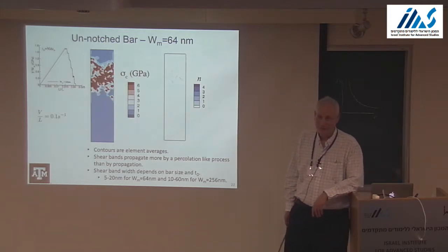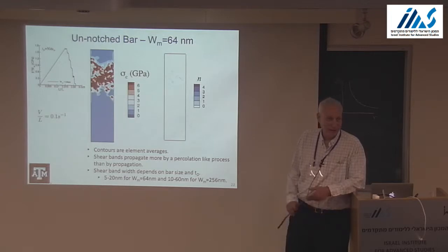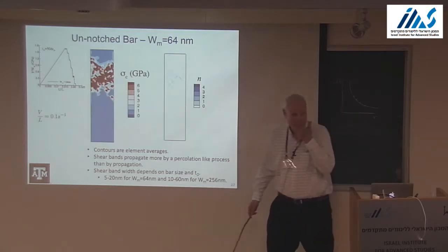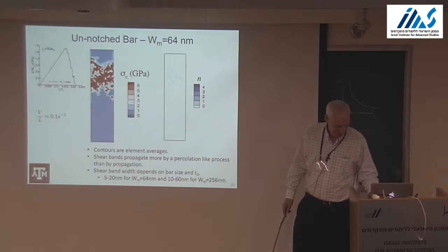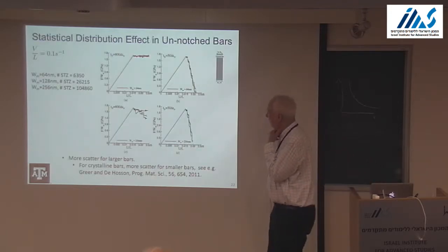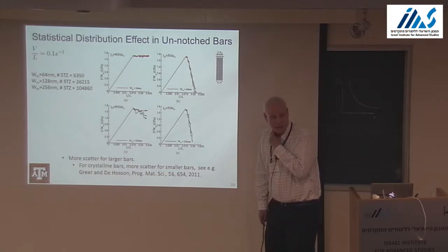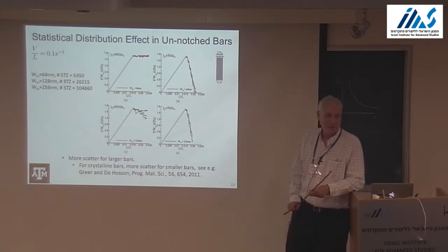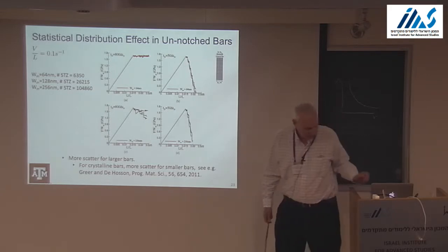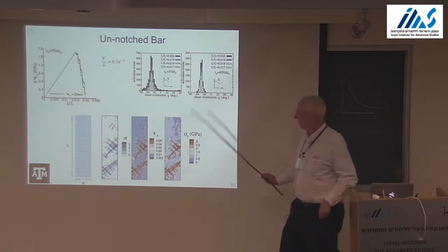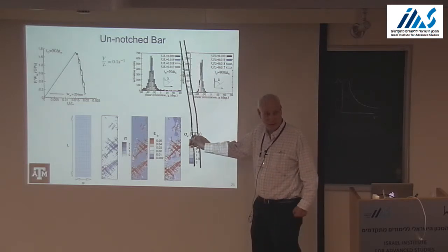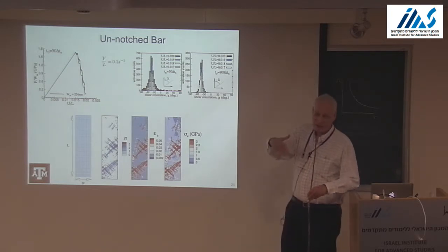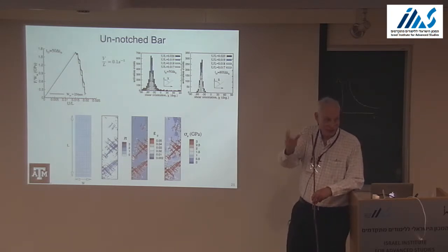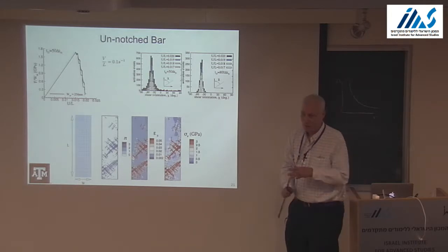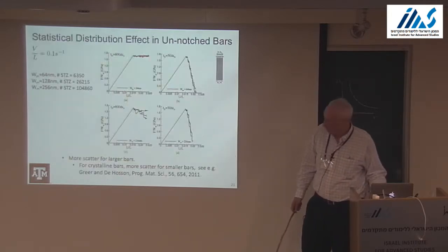Not on tension, not on the axis, only on shear. It's not quite 45 degrees. Here's 45. In this simulation, it's close to 45, but not quite exactly. It's peaked around 45, but there's a distribution, because when you activate something, it changes the local stress state, which changes the maximum shear direction. So what we find is it's not exactly 45.